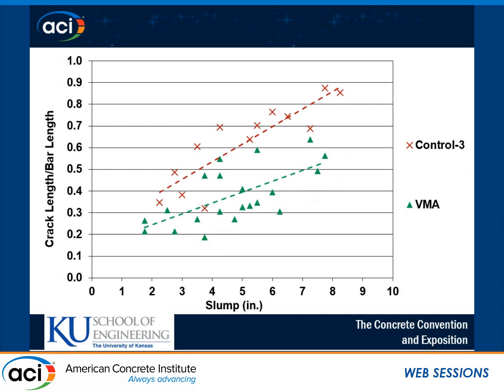For the series that we looked at the VMA with, we used a different control there, so that's why we have a different line and different numbers there to present. But for a mix that's more cohesive when you add a VMA to it, it's something that will behave like it has a higher slump than it actually does, we can see some benefits in terms of settlement cracking.